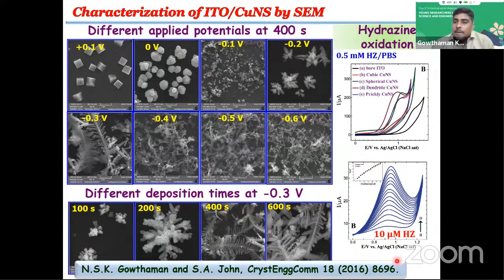Here, the dendritic nanostructures D exhibited high electrocatalytic activity towards hydrazine oxidation, and this electrode is highly sensitive from 10 micromolar to 150 micromolar addition of hydrazine without changing the oxidation potential, and gives a very linear curve.